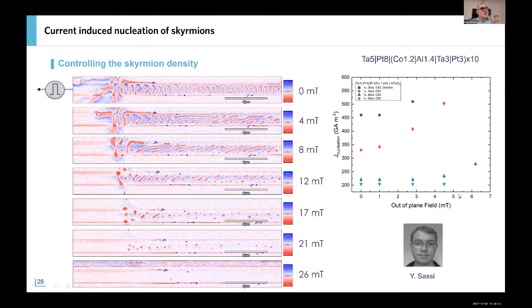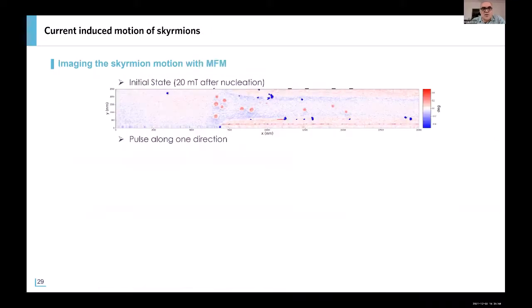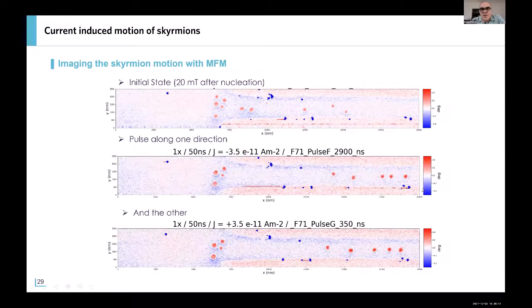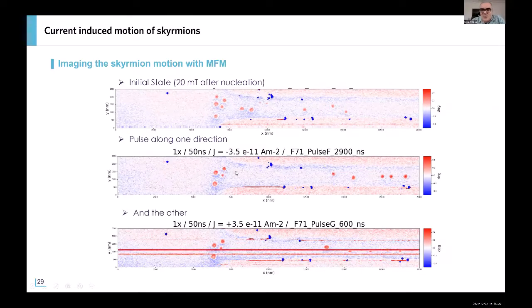Okay, so the message is that a combination of current injection, because the nucleation is mostly thermally activated, and magnetic field is the good way to proceed to stabilize the skyrmion. And then we can move the skyrmion. So again, these small movies that we show are obtained by MFM. We have an MFM image, we inject the pulse, we do a second image, and so on, and we can make some movies about the skyrmion. So we do see skyrmions after the nucleation I described before. And okay, here it should have a movie, sorry.